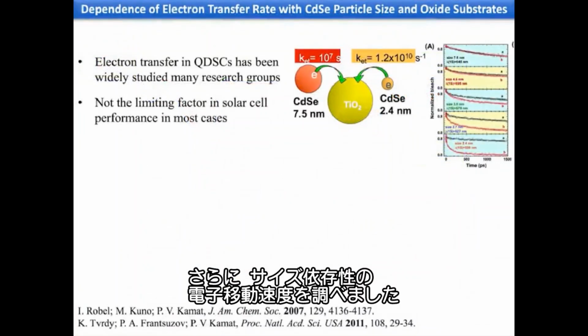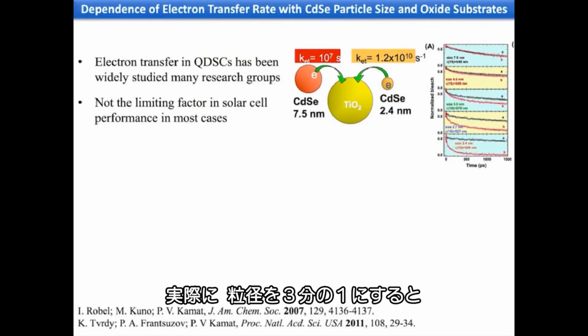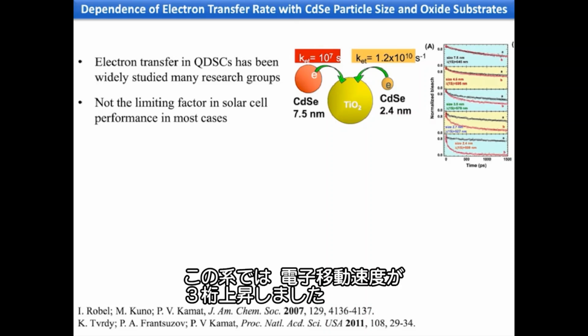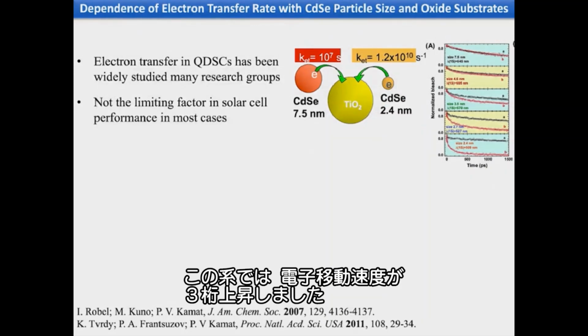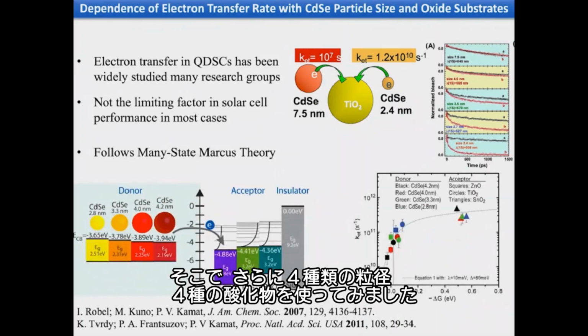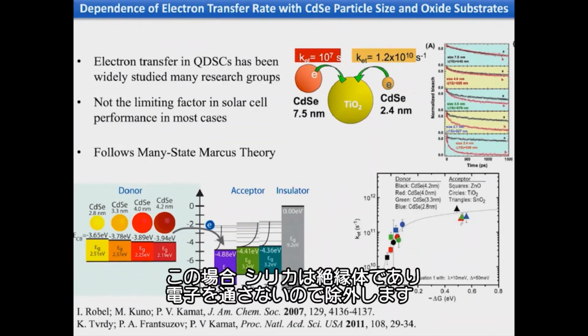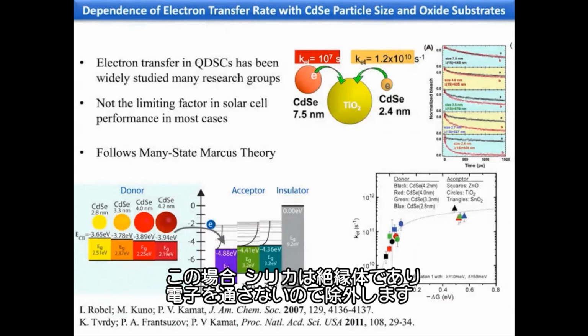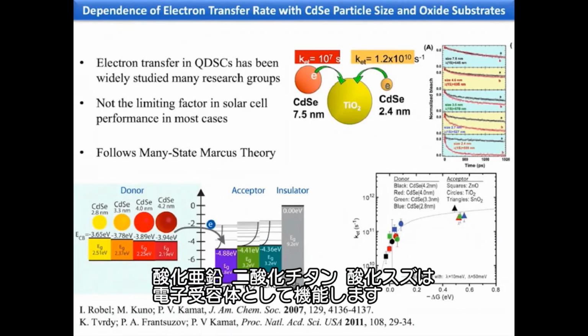We further studied the size dependent electron transfer rates, and indeed when we decrease the size by a factor of 3, we saw an increase in the electron transfer rate of 3 orders of magnitude. And in fact, we went ahead and used 4 different size particles and 4 different types of oxides. In this case, silica served as an insulator where we cannot transfer electrons, so that is our reference, and zinc oxide, titanium dioxide, and tin oxide served as electron acceptors.